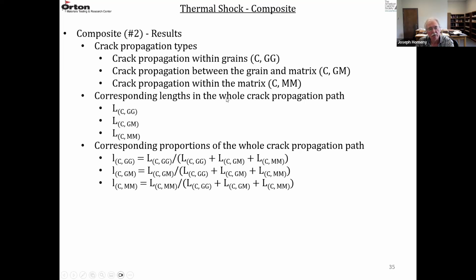And then they looked at the length in the whole crack propagation path for each one of these types of crack propagation behaviors. So they had a capital L GG, a capital L GM, and a capital L MM. So this was propagation within grains, propagations at the interface, and propagation in the matrix. And then they got a percentage here, the corresponding proportions of each one of these crack paths relative to the whole crack path. So small l GG is the portion of the crack that went through coarse grains. This small l GM is the portion of the cracks that went through the interface. And this small l MM is the portion of the crack that went through the matrix.